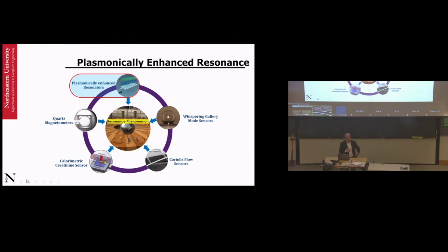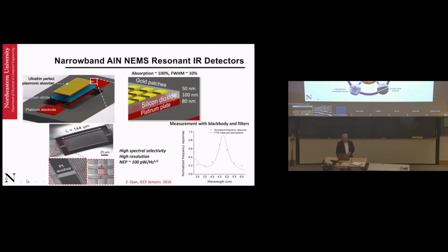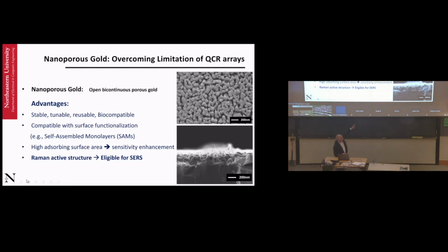And the last part that I would have just spoken about, but this is too complex at this point, is that you can also have another kind of resonance, which is called plasmonic resonance, which is also very helpful in improving sensitivity, especially for biosensors. So what we in my group have done is made this nanoporous gold. This is nanometer scale gold. It looks like a sponge. It really gives you a large surface area and lots of openings, because of which you can actually get plasmonic enhancement of signals.